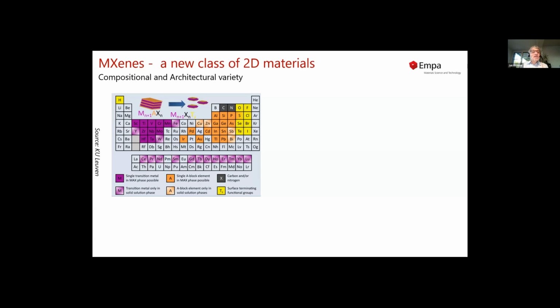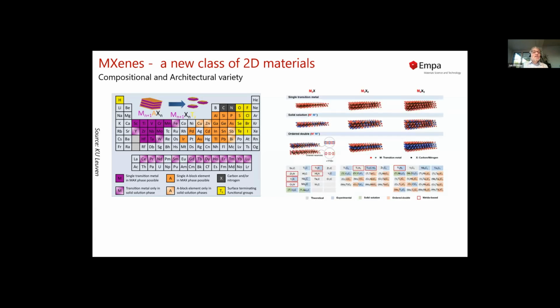The transition metal can be any of these transition metals that are indicated in violet here. These materials can be functionalized with a lot of different functional groups. The backbone is carbon or nitrogen, or even mixtures of that. So you can not only use one element, but you can also mix different elements. You can make solid solutions, ordered or disordered double layer structures, and sheets of different thickness. And what people are currently working on are the so-called high entropy MXenes, where you introduce more than 4 or 5 different transition metals into one of these